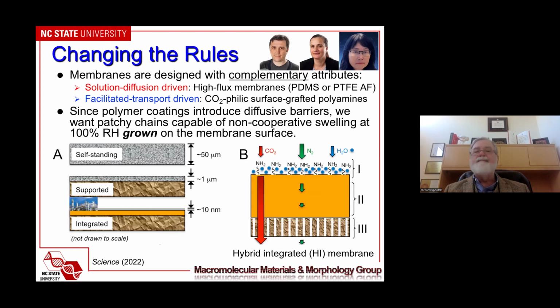And now, in the presence of water, this surface becomes highly swollen. It essentially becomes a nano sponge, and it loves CO2. So much so that now the amount of CO2 going through is much, much higher than what we have for nitrogen. This type of membrane we've called a hybrid integrated or HI membrane.